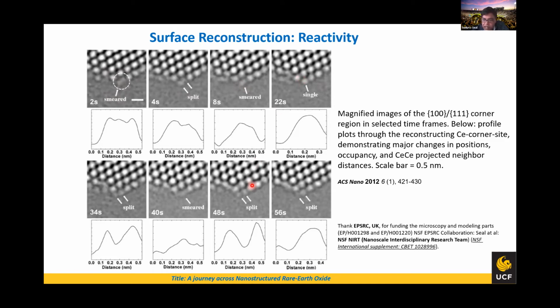One of the most important things that I can infer from here is that we work on radiation resistant materials and have been funded through NASA before. And this is very important because if you can design this material with a terminated crystallographic plane, you can now design how this material will behave under radiation. One of the interesting things going on here is that these big white blobs are nothing but the cerium atoms. Oxygen is very hard to image here. But during the radiation, the cerium-oxygen chains are moving. They're creating the reduction process of CeO2 to Ce2O3, which actually facilitates the quenching of a dipole moment here. And then finally, the 100 surface energy becomes very similar to 111, and comes to some kind of stability as well, thermodynamic stability.